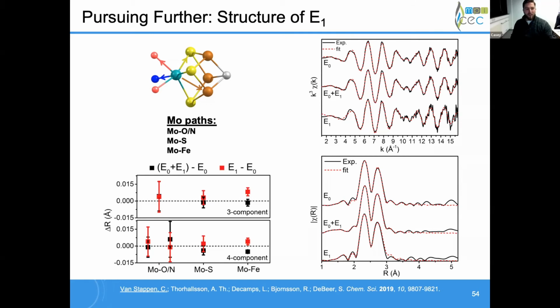And so if I look at the distances that I fit for molybdenum, we find that really nothing changes. This is what we would have expected since we don't have a change in oxidation state. And importantly, in this two-point fitting process, I find that even though it looks like on either side maybe something small and significant is happening from the molybdenum-iron standpoint, they contradict one another,